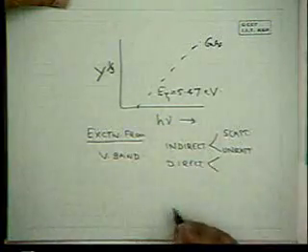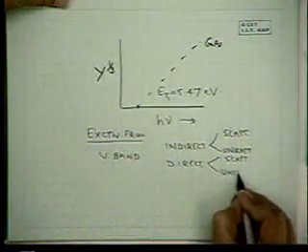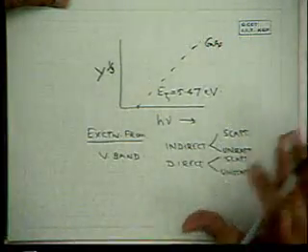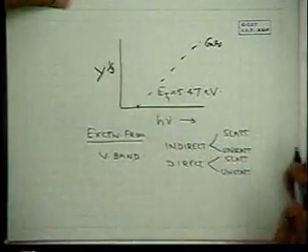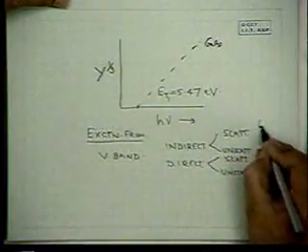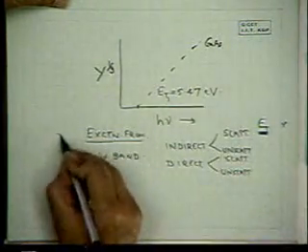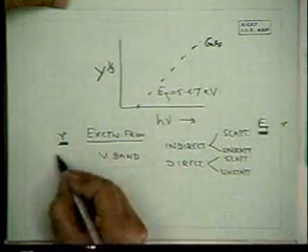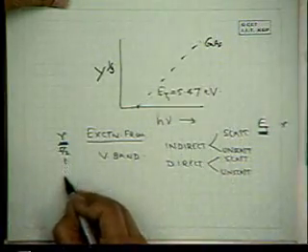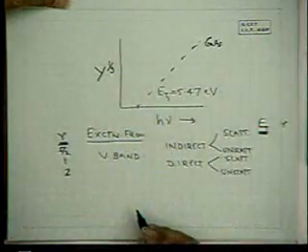Okay. So one can carry out a full-scale analysis exactly as in the case of optical absorption, depending upon the band structure of the material, and get values for the threshold and this R exponent. Okay. For example, this R exponent can be 5/2 or 1 or 2, depending upon the processes involved.